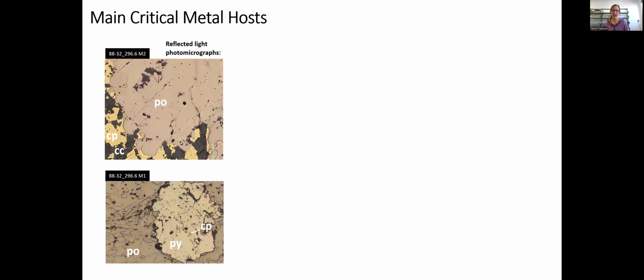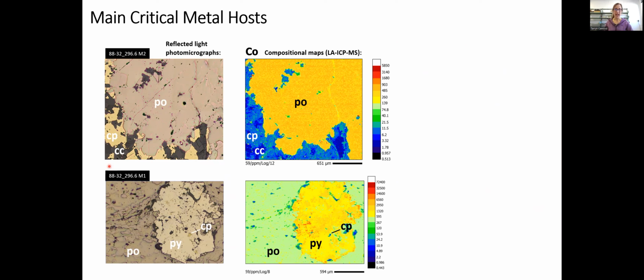And just to get started, we're trying to figure out what are the main hosts of the critical minerals in this deposit. So we start with some photomicrographs showing, again, pyrrhotite, the brownish color, pyrite, which is the pale yellow, and then chalcopyrite, which is the bright yellow over here. Ooh, my pointer's all over the place, sorry. And if we look at the compositional maps, in this case, these are cobalt composition maps, we can see that pyrrhotite hosts quite a lot of cobalt, several hundred ppm.